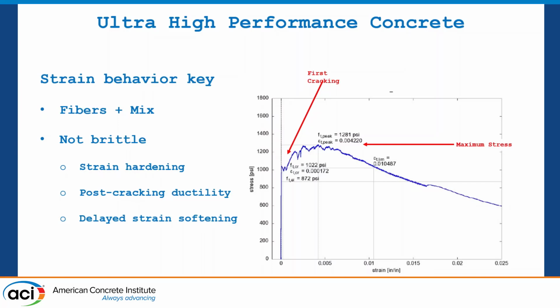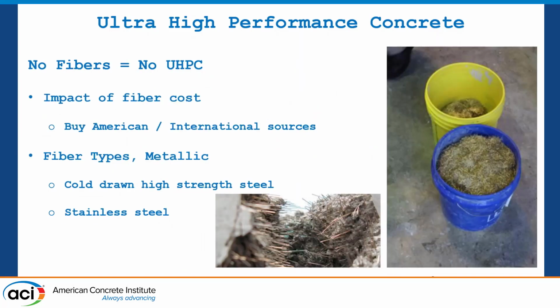This is an example. We did a test on some UHPC at 7 days, and this is a real-life example. We have fibers in our mix. This is with steel fiber. We get our initial cracks here at about 1,000 psi, and then it peaks at almost 1,300, about 1,280, and then you get this delayed strain softening of a failure. So this is what UHPC is all about. This is what sets it apart. It's not brittle, and you get some ductility out of it. Like I talked about, fibers are key. For UHPC, steel fibers and high strength fibers are going to give you that response that we're looking for, that strain hardening.